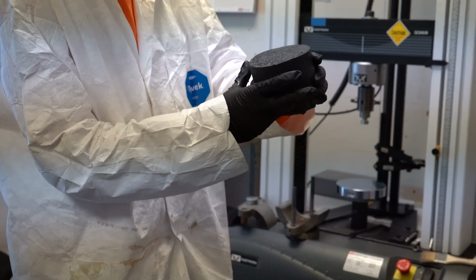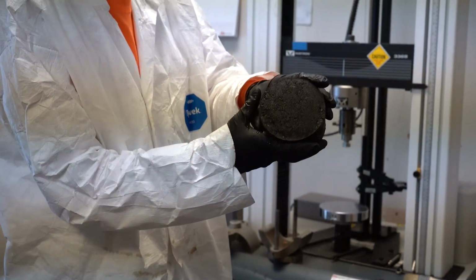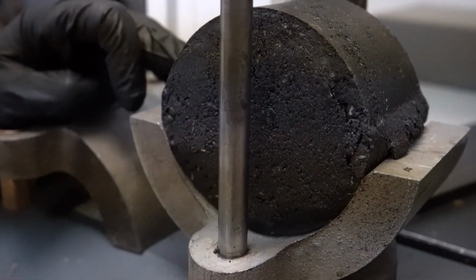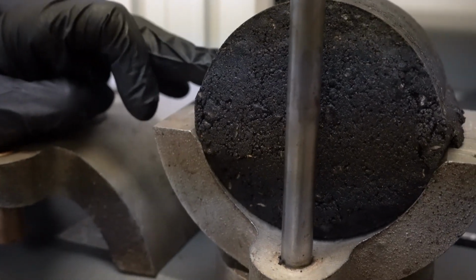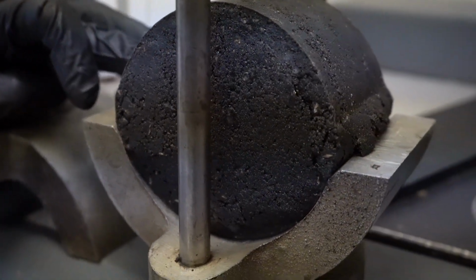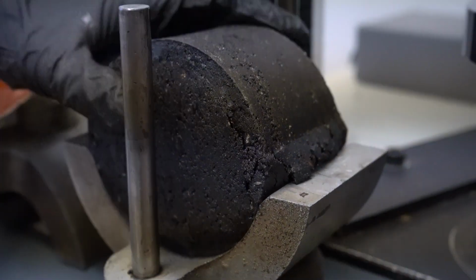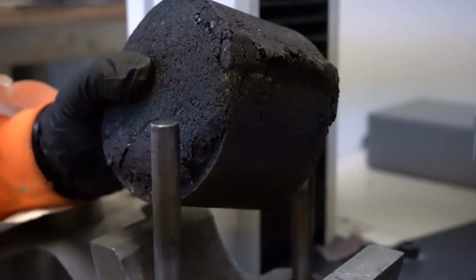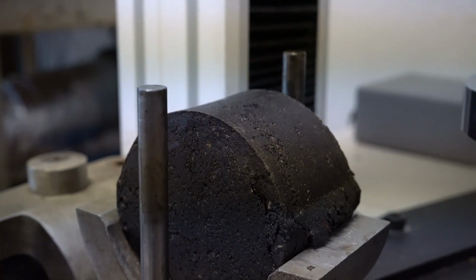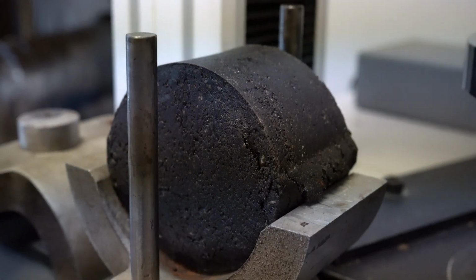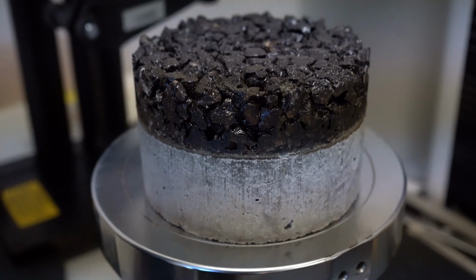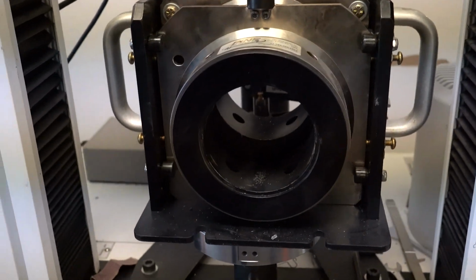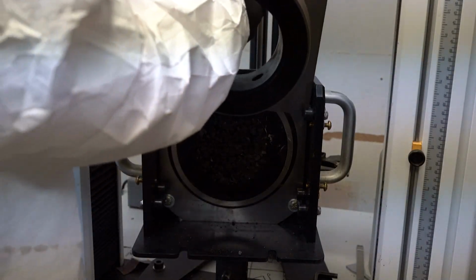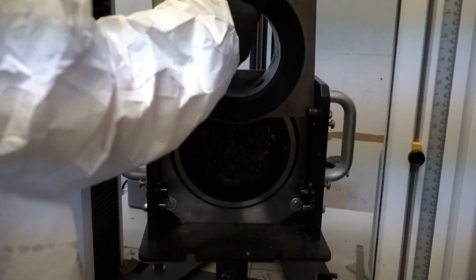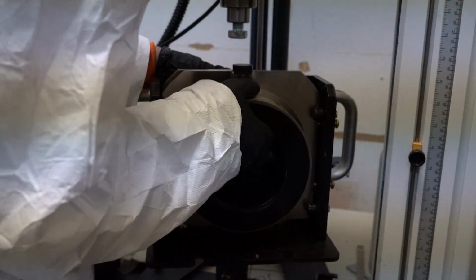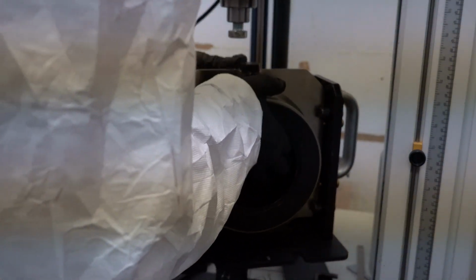Okay, after the test, the sample has been compressed and failed in this way. After the Marshall stability test, for the uncured sample, as you can see, it has been squeezed in this way, and the Marshall strength is about 3,000 pounds. 1/8 of an inch, so we put the other plate on top. We push it inside.